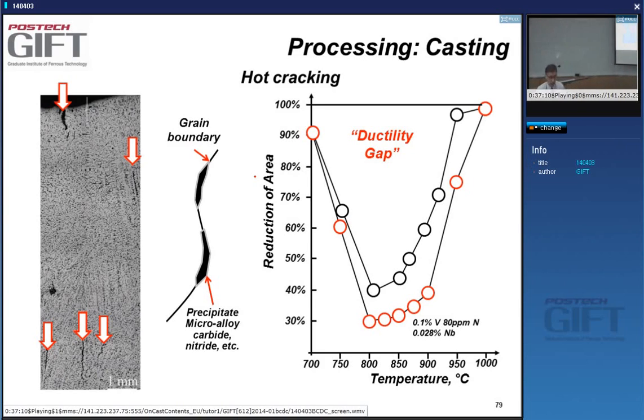You're cooling the material, and we know that in our composition, we, for instance, added niobium or vanadium because we want to do some precipitation hardening. These compounds precipitate while we're cooling the slab and casting it. Because we're cooling very slowly, they tend to form precipitates at grain boundaries, and they weaken the grain boundary strength at these very high temperatures. It's not a problem at room temperature because you control the distribution of these precipitates. But at high temperature, they form where they want and they're very coarse. So we observe a ductility gap.